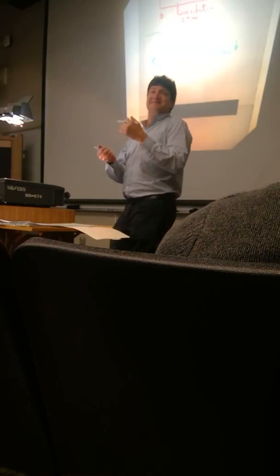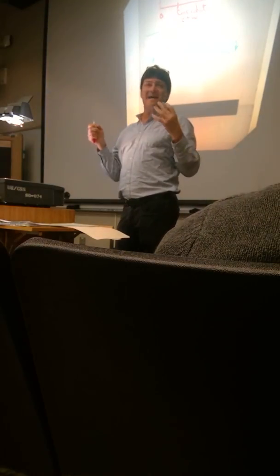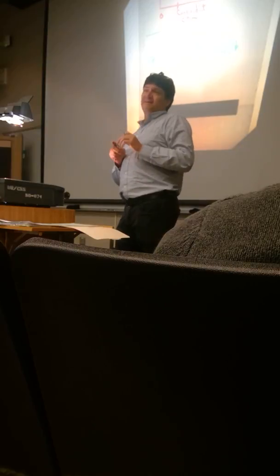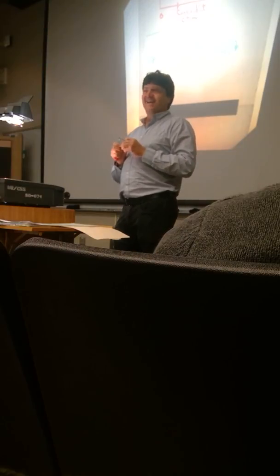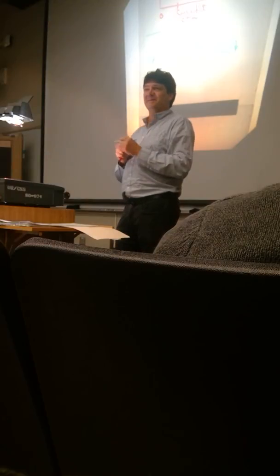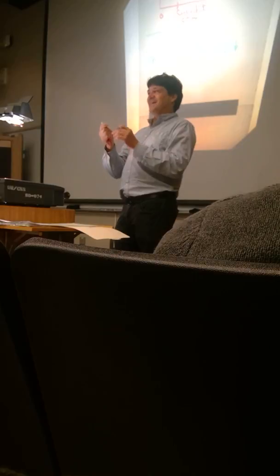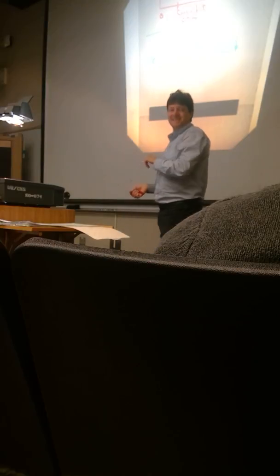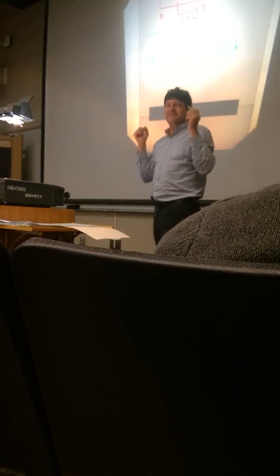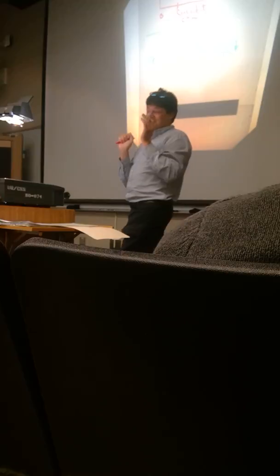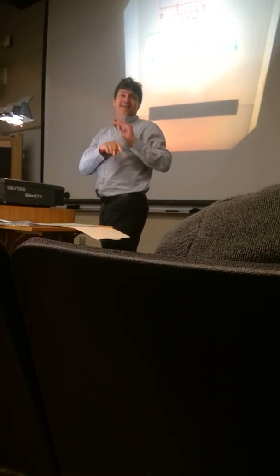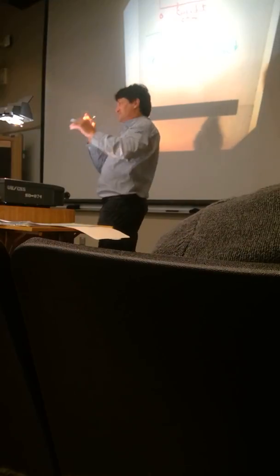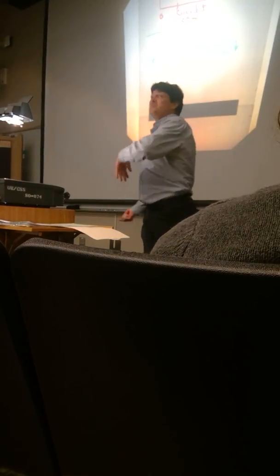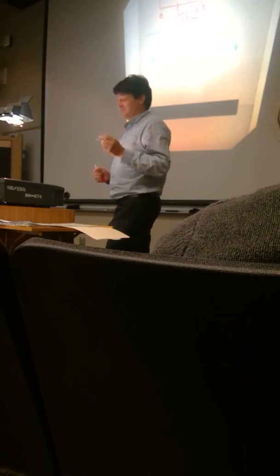because when you think grain size, you're thinking, okay, what's the radius or diameter of your grain, right? If you talk ASTM grain size, it's inverse. You guys learned that when you did polishing? So ASTM grain size is how many grains you see through the microscope. So if you have a large ASTM grain size, it means you're seeing lots and lots of grains through the microscope. So that means it's actually a smaller grain diameter. When I talk grain size, I'm not talking ASTM. But you just want to make sure if you get in industry and they're talking ASTM grain size, you know that it's inverse to the actual diameter of the grain.